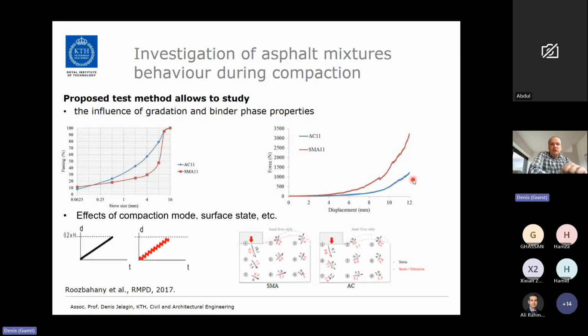We also looked at different compaction modes, monotonic compaction versus kind of vibratory compaction, where compactor load is applied along with sinusoidal vibration superposed with monotonically increasing load. And one can see in the test that this vibration both reduces uplift significantly and also affects vertical deformations in the material quite a bit, both for SMA and asphalt concrete materials. So reasonably simple test method, in our opinion, more representative to what happens in many field situations. One experimental tool which has been proposed a few years ago.